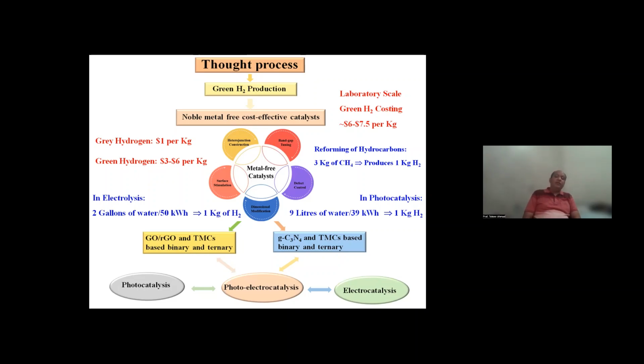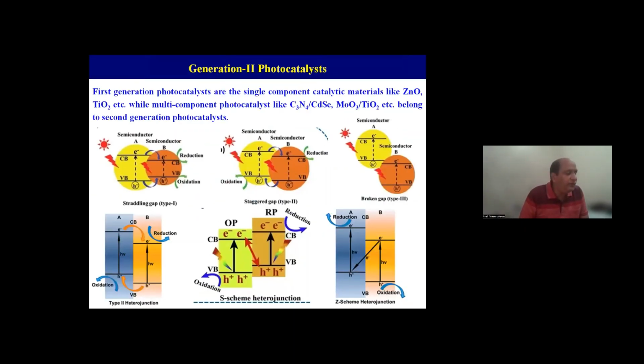have to go. So we have to design metal-free catalysts by taking graphene oxide and reduced graphene oxide or graphitic carbon nitride as the carbon support, and the TMCs and oxides as the other support to make binary and ternary heterostructures, and then apply the photocatalysis, electrocatalytic and photoelectrocatalytic applications of these materials.